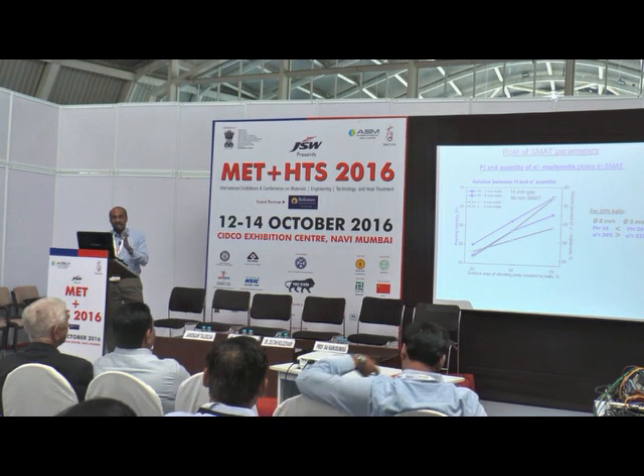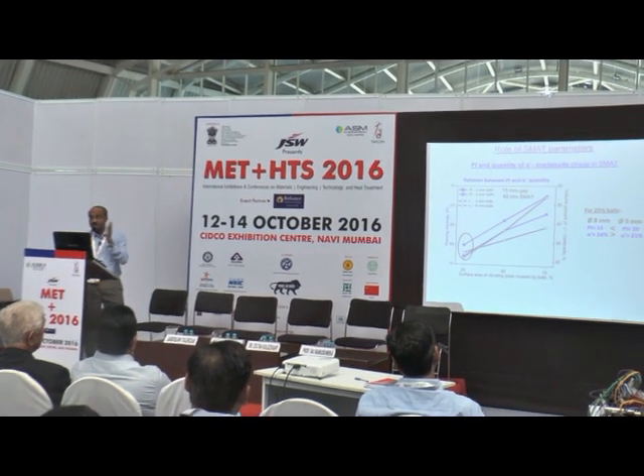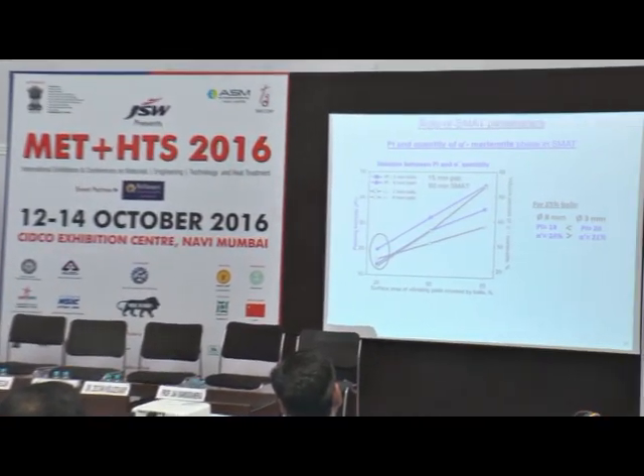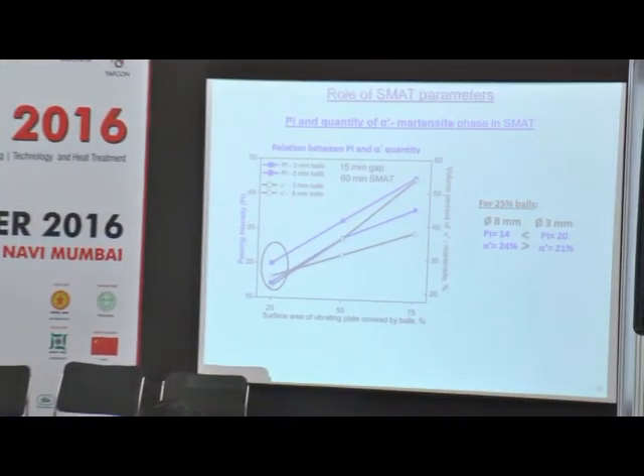That is, the pinning intensity will tell you. We got a perfect correlation between pinning intensity and quantity of martensite. Here you can see that as I increase the percentage of ball, my pinning intensity also increases, which is shown by the blue line. So pinning intensity increases, and at the same time, quantity of martensite also increases. As I mentioned, martensite quantity is very much dependent on the amount of strain. So as I increase the ball, increase the PI, strain is increased. That's why martensite quantity increases.